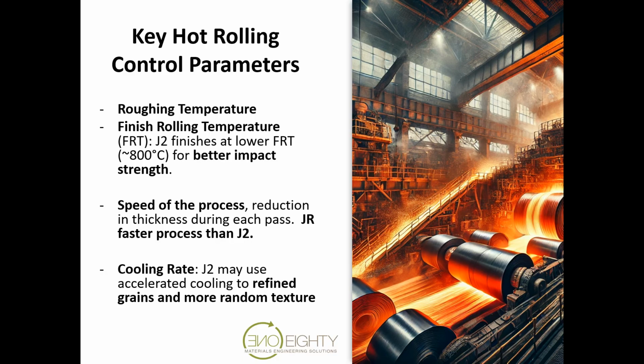So the key parameters in rough rolling for J2, it's not on here, sorry. The rough rolling happens at a higher temperature than for the JR material. J2 is finished at a lower temperature, which means that the whole process takes a little bit longer, because they're not able to apply the same amount of reduction in thickness with the strain applied during each pass, since the material is not running as hot as when they produce JR material. So obviously when the material is hotter, you can put more strain into it with each pass without the coil fracturing. The last thing you want is for that coil to fracture in half, because then you're just going to take it off, throw it away, remelt it and start again.